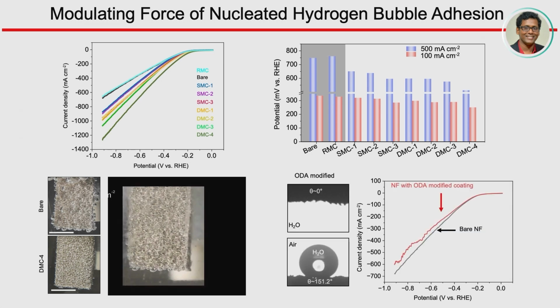Now, one of the referees asked, how do you show that the coating doesn't have any catalytic contributions? So for that, we did this simple study here. See this bare coating, that doesn't really show this kind of performance, right? And then just the simple hydrophilic modification, which is not known for catalytic ability, gives rise to this improved performance. To further verify what we did, we took another modifier, ODA, octadecylamine.